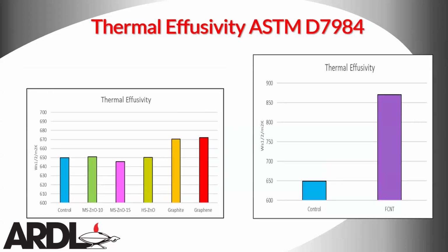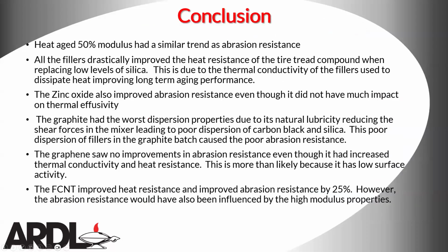We also looked at thermal effusivity, and once again had to break it out into two charts because the functionalized carbon nanotube was so much higher. And you really don't see a difference with the zinc oxide. So you do see a bump in thermal conductivity, so it's able to move heat throughout the part. But as far as thermal effusivity goes, it's not really able to dissipate it very well from the surface. But you are seeing higher thermal effusivity with your carbon-based ones, your graphite and your graphene, and then ultimately much higher with the functionalized carbon nanotube.